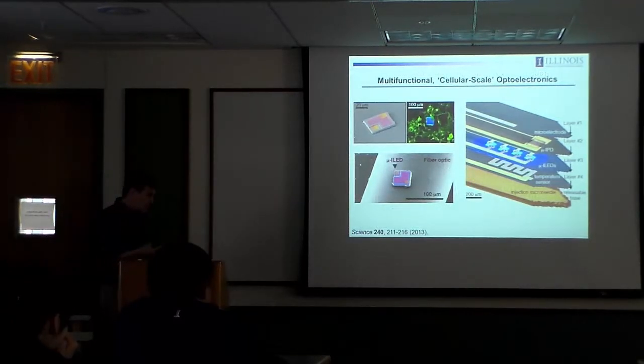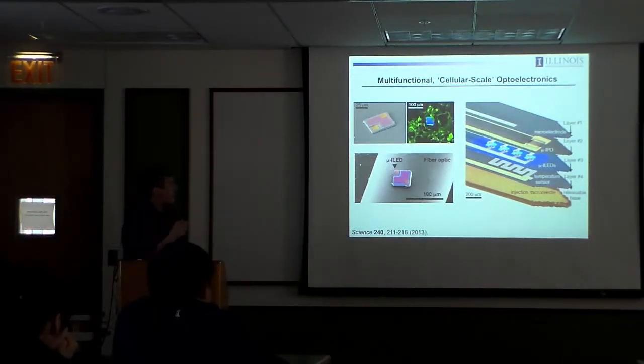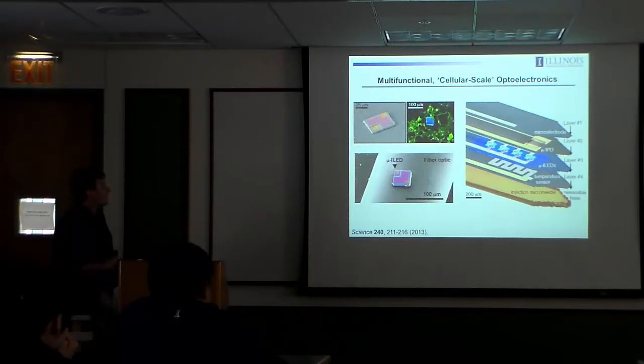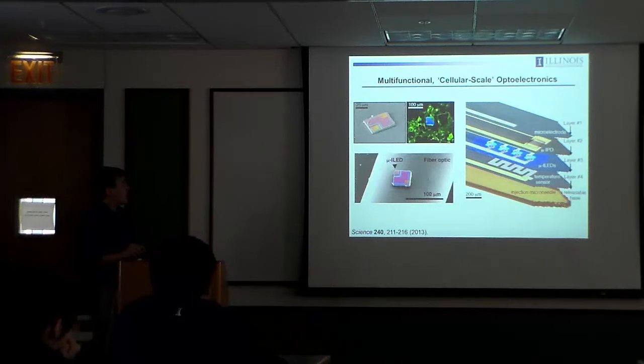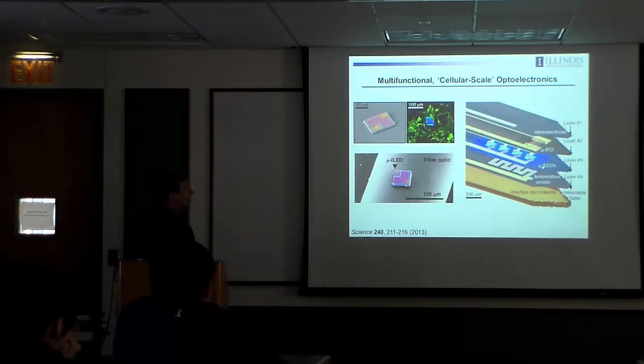And our idea was to say, throw out the laser, throw out the fiber optic cable, and put active LEDs down into the brain and use wireless control and harvesting strategies to enable really free moving animals to be modulated by optogenetics. So use the ideas I just described to you. Very tiny LEDs, almost cellular scale in their dimensions compared to fiber optic. This is kind of what it looks like. And then mount them on ultra thin filaments of polymer. So narrow strips, very thin polymer substrates, do the transfer printing, do the edge over metallization and interconnect, and form little arrays of LEDs such that the entire polymer filament here is only maybe 5-6 microns thick.